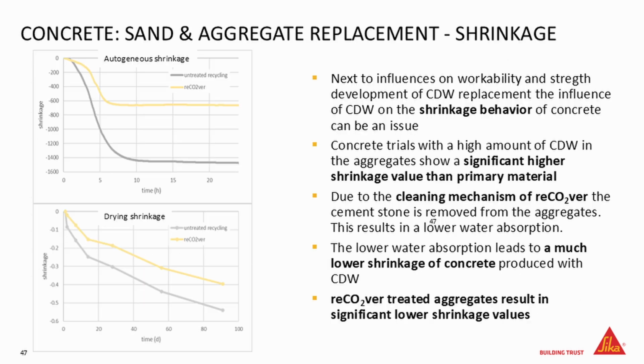Another aspect of recycling concrete is the shrinkage aspect. This is also a result of the water demand of the aggregates. When the aggregates suck the water or work like a sponge, that often results in shrinkage cracks. So we looked at that. We looked at the autogenous shrinkage, so we measured from time zero when we filled the concrete, and we measured the drying shrinkage, which is from the Swiss standard. The measurement starts after 24 hours, but this is in the standard.